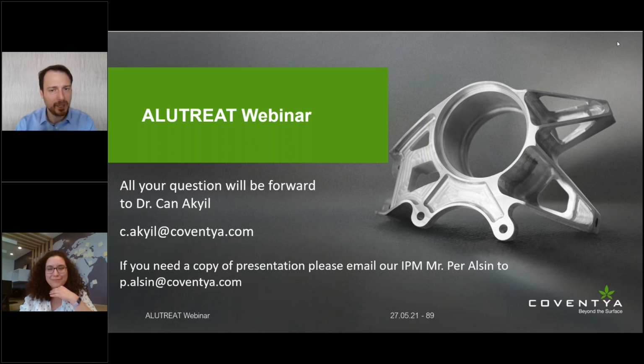I would say somewhere in between. Therefore, we know as a rule of thumb, when we are matching customer samples, when we send out a recipe, which is a daily business for Ms. Pinar, we warn our customers the voltages that we apply are maybe a couple of volts lower, and also times are at least half shorter. Say when we say 6 minutes, you would end up with about 12 minutes.